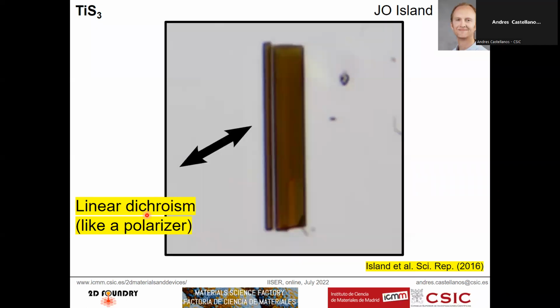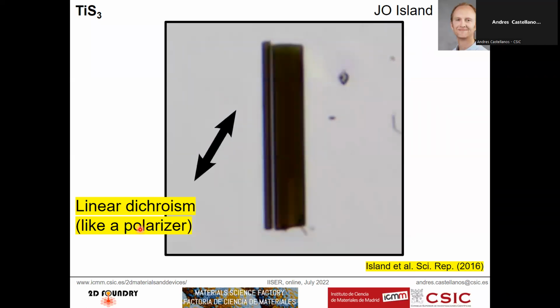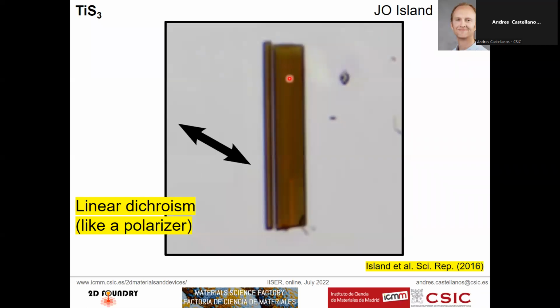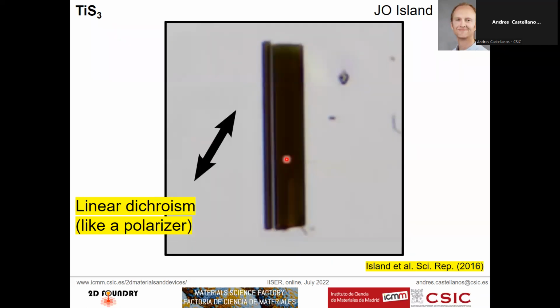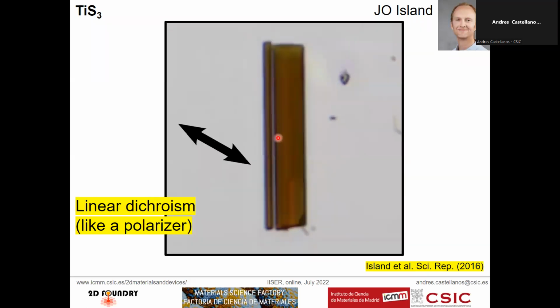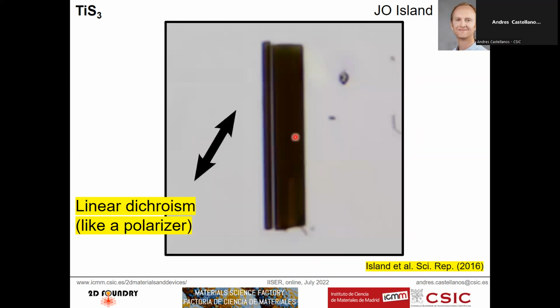So this is similar to a metal wire polarizer. When you're polarized along the B axis, that is the direction in which the electrical resistance is lower in titanium trisulfide. So basically you can excite electrons going back and forth, and you can quench the electromagnetic field. In this other direction, the electrical resistivity is much larger. Therefore, it is much more difficult to excite electromagnetic waves in this direction.